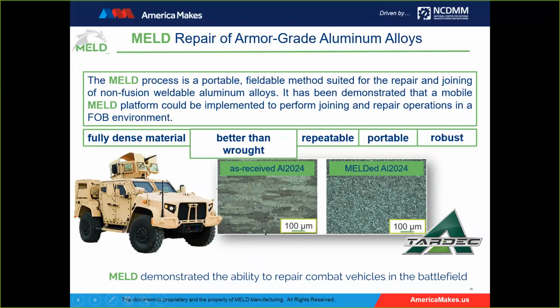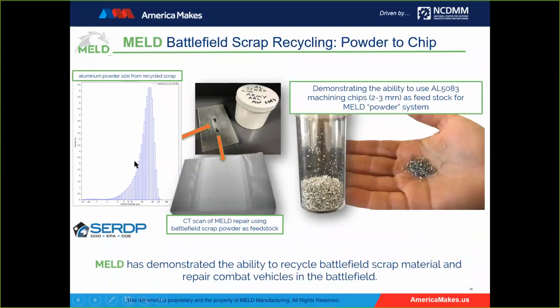And the main purpose was to demonstrate the ability to repair combat vehicles in the battlefield, and we passed this first round of tests. We've gone into a SERDP project where they're actually taking the battlefield scrap and shredding it into little chips, little scrap pieces. You can see it's not very attractive. Again, we said any powder type. We're not picky, from coarse to fine, and that certainly meets the definition of a coarse material. And we demonstrated the ability to print that recycled material.